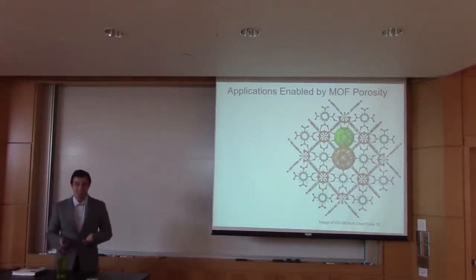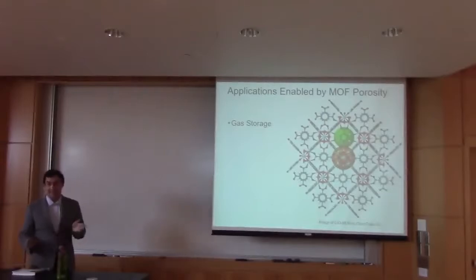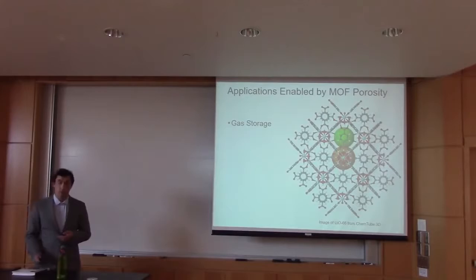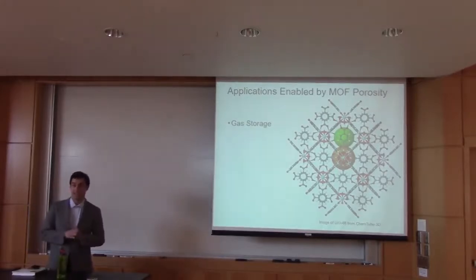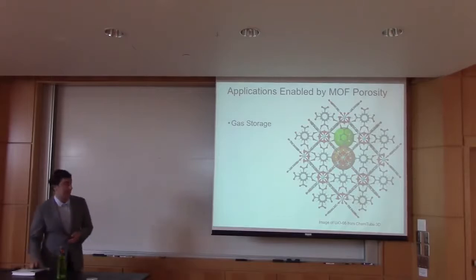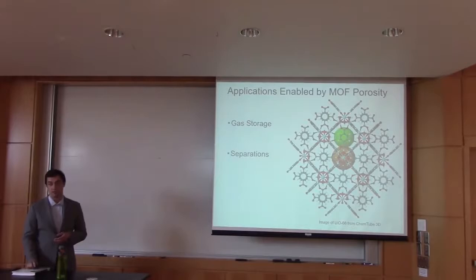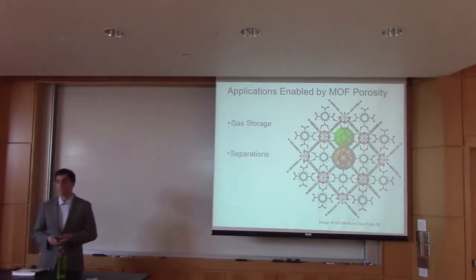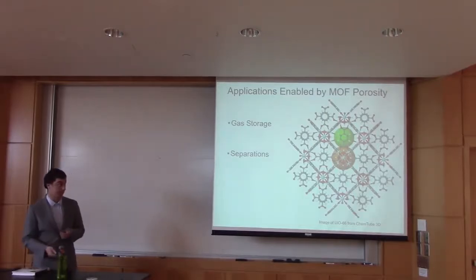So what this does, the first and foremost exciting thing is with gas storage, and this has been applied already. In all those nooks and crannies, you can hide a lot more gas than in gas cylinders, which is how we traditionally store gas, and thus store more gas at safer pressures. You can also use it for separations, which is traditionally a very energy-intensive process. And now you can just pass a gas through a metal organic framework, and it can have a higher affinity for one gas compared to the other and get separation done that way, much more energy efficient.